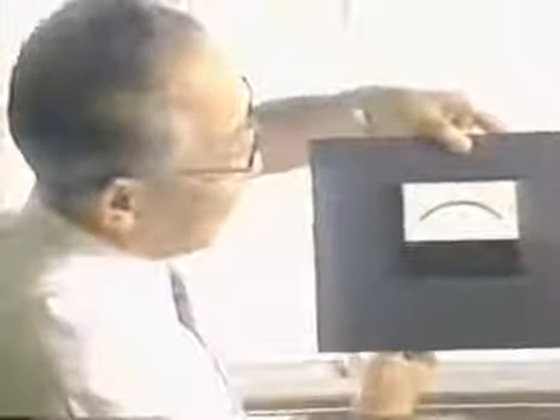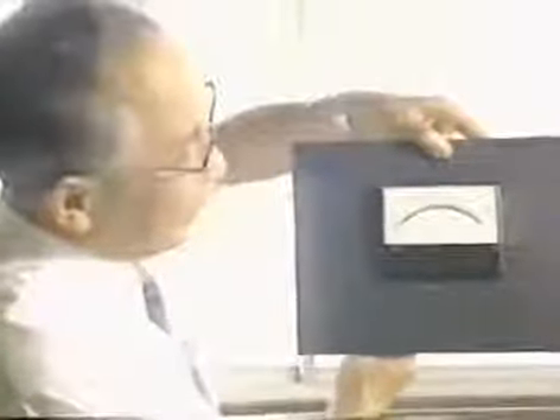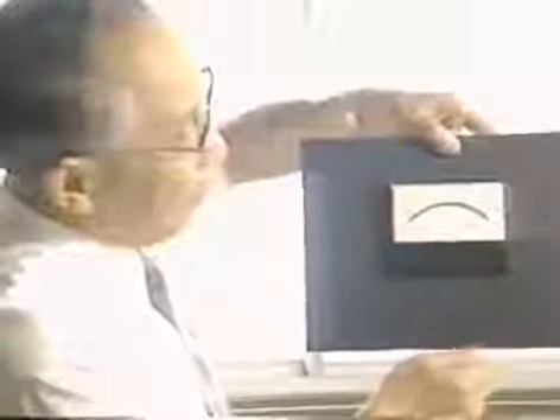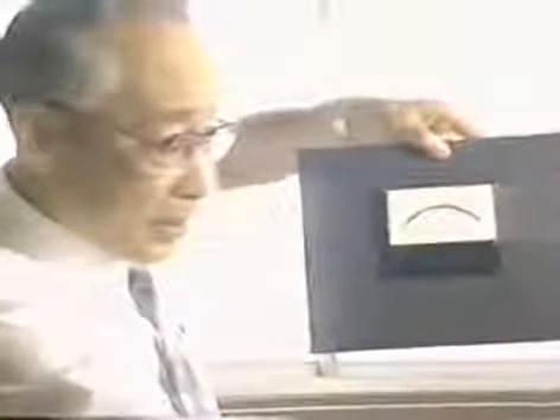We were unable to buy advanced American equipment. The temperature gauges at that time were rounder and bigger than this, and had a large needle. When we raised the temperature, this needle shot right up to 600 degrees, then 800 degrees, passing the melting point of germanium until it arrived at approximately 1,000 degrees centigrade. At that point, we lowered the temperature slightly. But as you can note, this needle mainly measures units of 1 degree, and 0.1 degree can't be seen. For that reason, no matter how many times you try, you'll fail at making crystals.